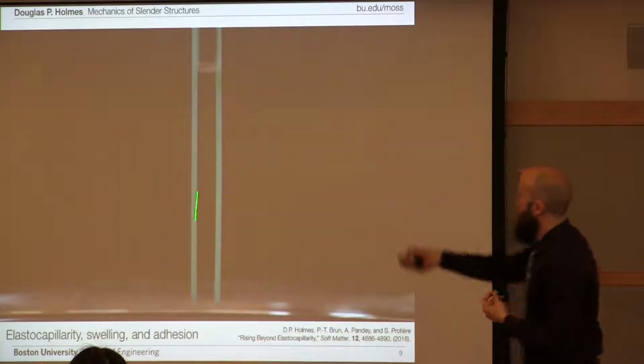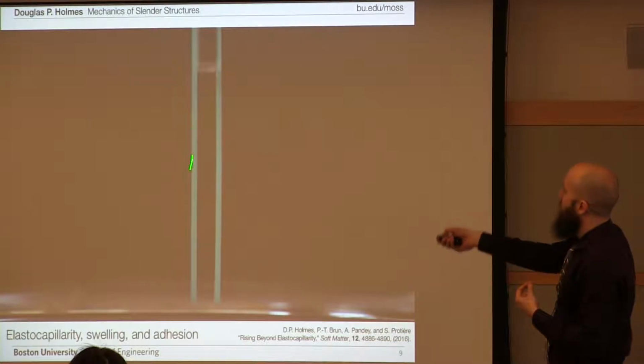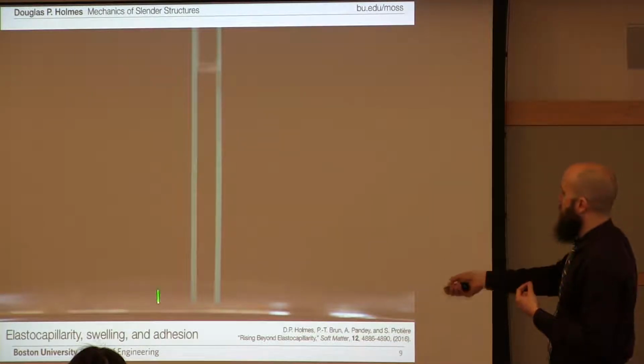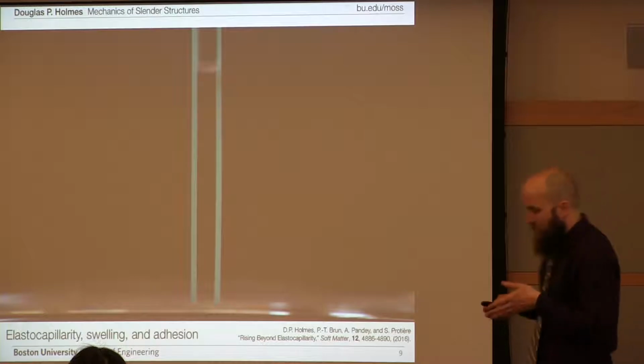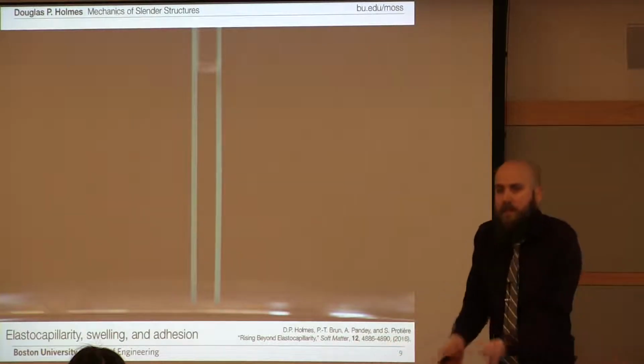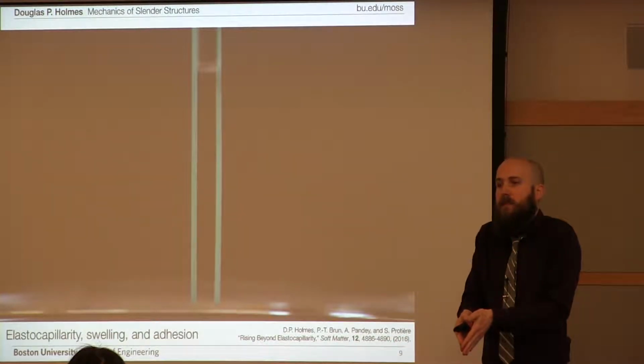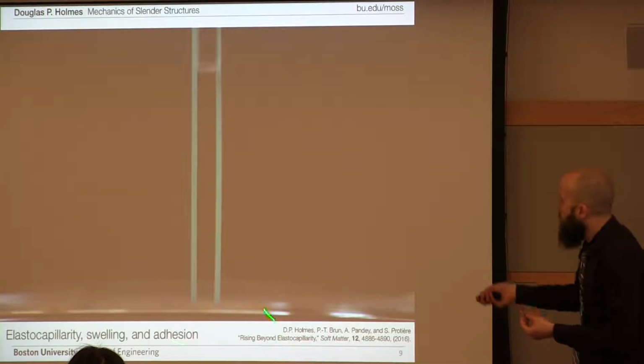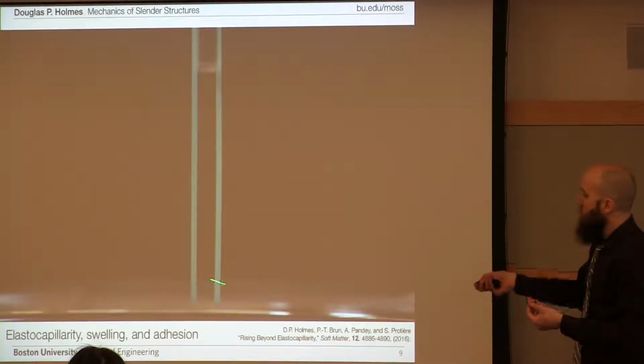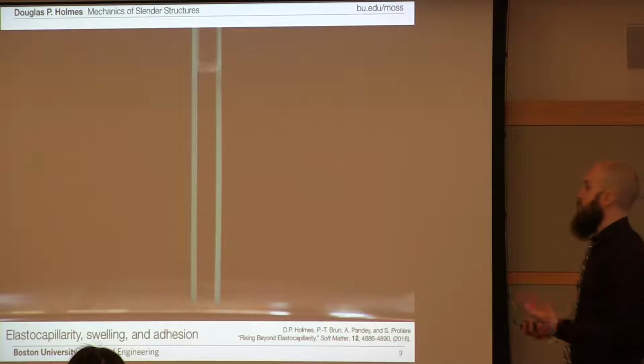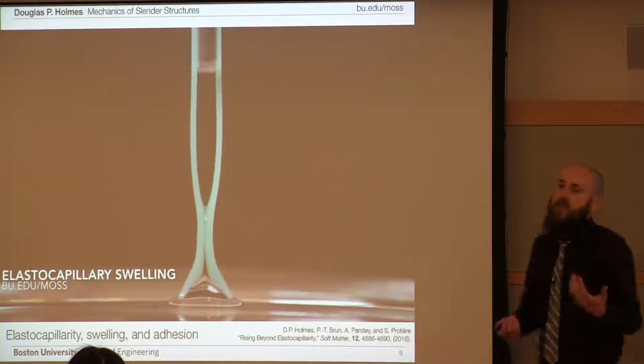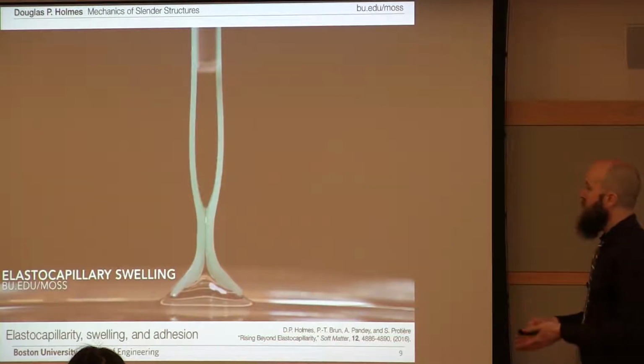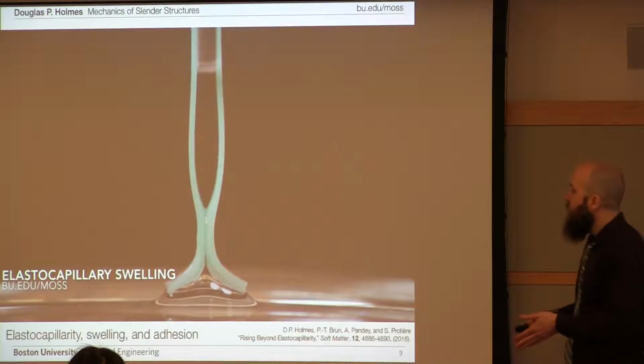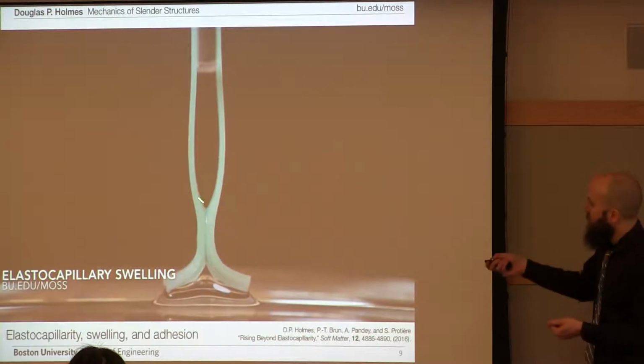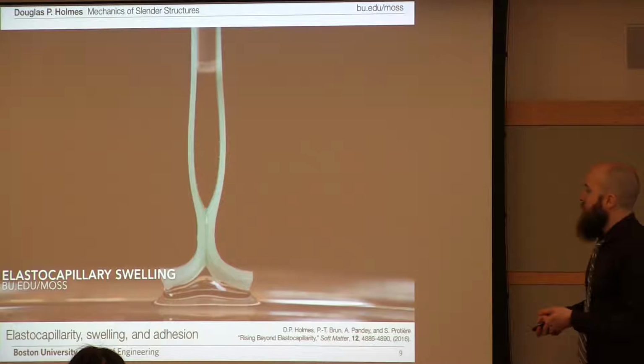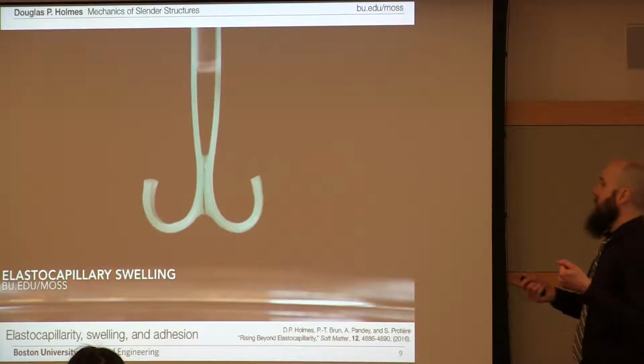And so what we did is we took a couple of sheets that are soft rubber materials. So this is silicone rubber. This is a bath of silicone oil. And we're going to dip them in the silicone oil, and we'll expect these things to coalesce due to elastocapillarity. But then because these materials are compatible with each other, they'll induce a swelling in this structure. And the deformation changes dramatically. So instead of just coalescing due to surface tension, what you see is that swelling, or in this case a differential swelling, causes really significant bending deformations.